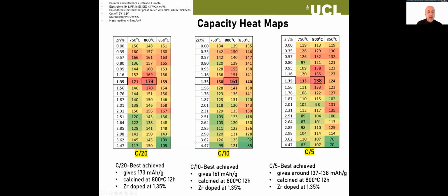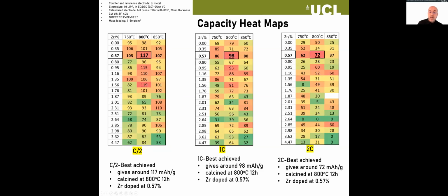At those charge or discharge rates, what we can see is that at the very slow charge or discharge, C over 20, it turns out that the 1.35, in fact across all three of these slow charge and discharge rates, is giving the highest capacity. So it's a sort of hotspot. What we're very interested in is actually the higher power, which is at higher C rate. So this is 2C. 2C would be half of 1 hour, so 30 minutes. For example, we're going to see 10C in a minute. 10C would be 6 minutes, so it's 60 divided by 10, which is 6 minutes.